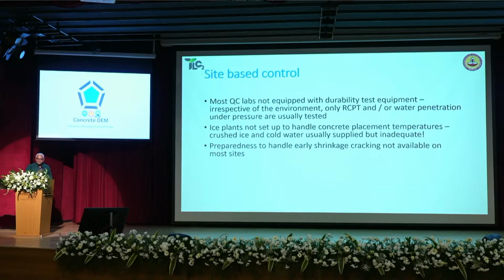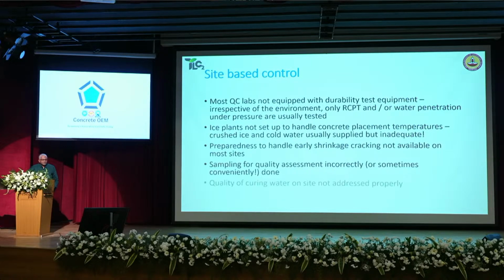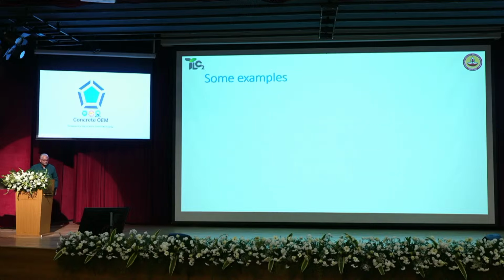And again, this planning needs to go in before, in case you really need to prepare a structure without cracking. And sampling for quality assessment is sometimes incorrectly done or sometimes not done at all. And quality of curing water on site is again not addressed properly. Now, again, this is something that we have seen very often, that curing water, if people start using groundwater which is rich in chlorides, it can result in disastrous consequences.